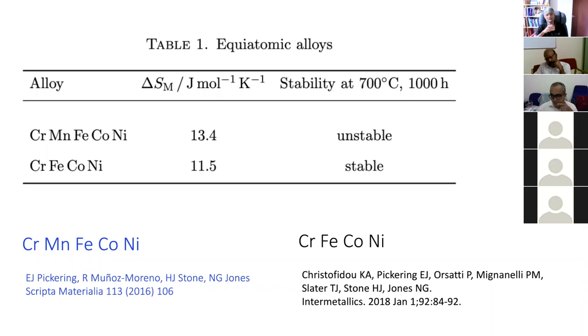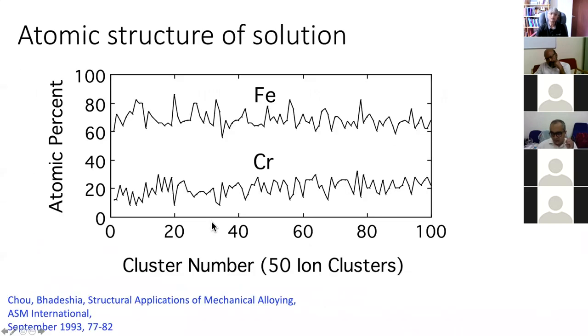So supposing we look at 50 ion clusters, and work out the average composition of those 50 ion clusters. This is a particular alloy system which contains iron and chromium, and we get variation in composition as illustrated, average taken over 50 ion clusters. So remember, there is no error in the chemical analysis here.